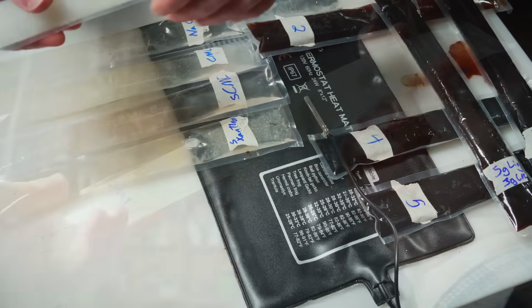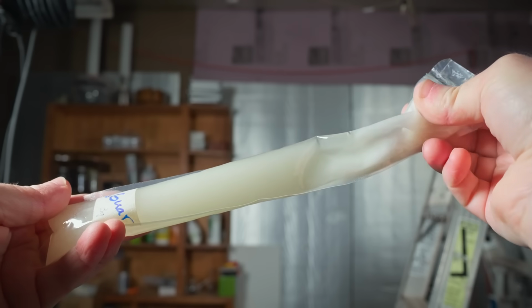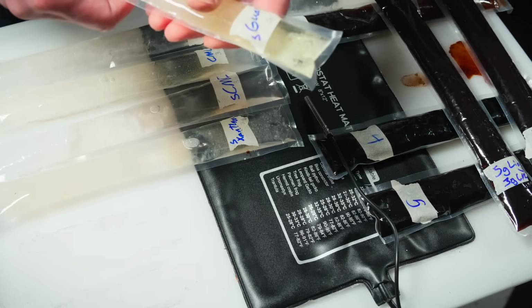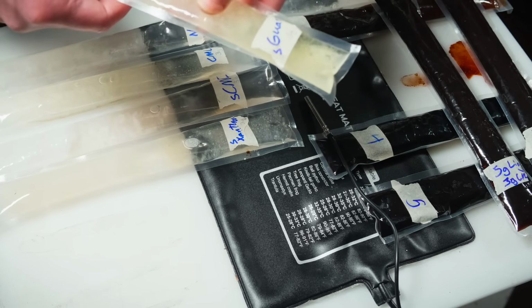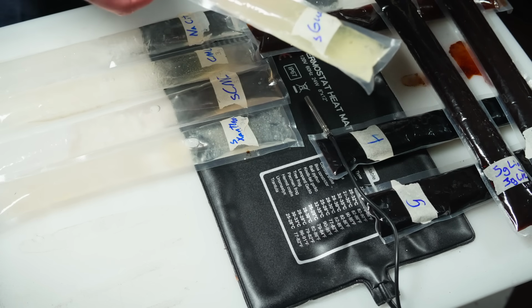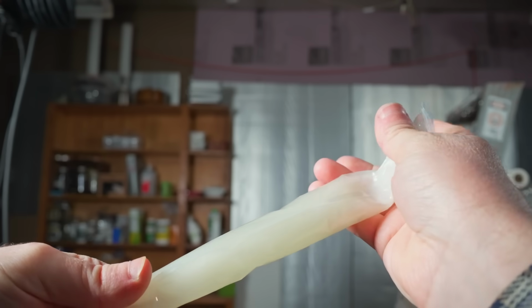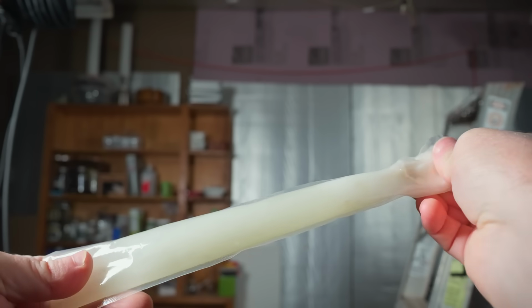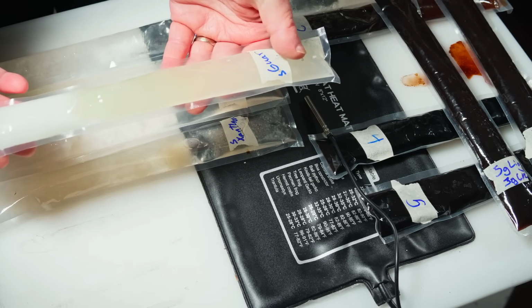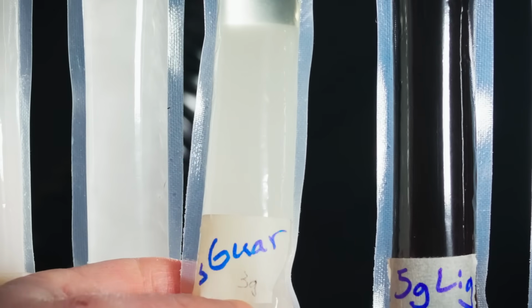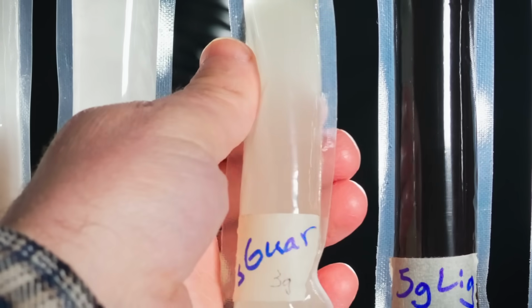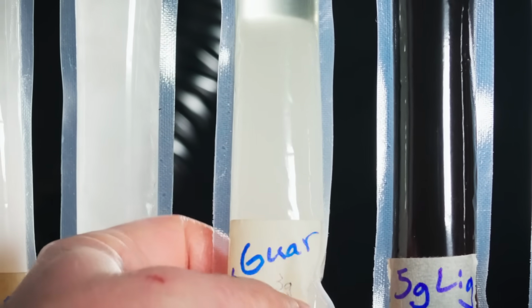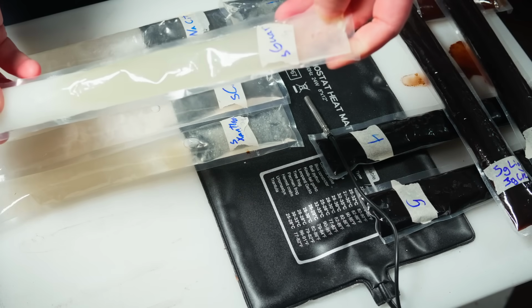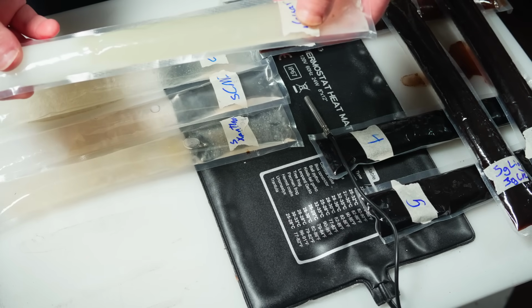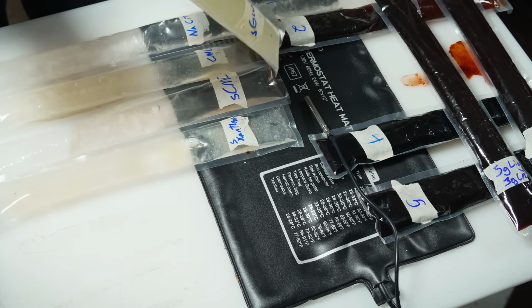Now, the guar gum actually froze this time. Wow. Okay, guys, this one is actually really soft. Oh man, that's so good. That is no crystal formation at all at that boundary layer. Wow. Okay, this needs some more testing because for some reason the guar gum sample did not freeze in our vertical cool down test, and I still have no idea why. But once it did freeze, it's just got such a soft texture, no rigid crystal formation whatsoever.